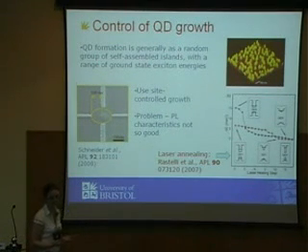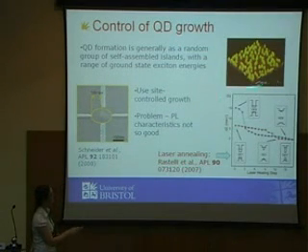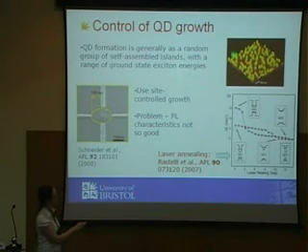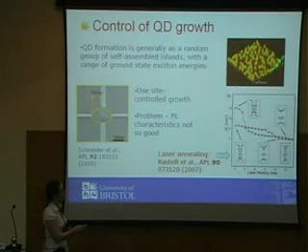So quantum dots then, the ones that we look at, these are self-assembled quantum dots. And self-assembly is a crystal growth technique which produces very high-quality quantum dots. So what you do here, I'm showing you an AFM image of these quantum dots. What we do is deposit indium arsenide slowly onto gallium arsenide. And that allows the formation of these so-called nano-islands here. Now these islands form spontaneously, and they're in a random placing on the crystal structure, and they also have a random size. And that size determines the emission energy of the quantum dot. So even though these have very good optical emission properties, this is not what we want. We want to be able to control exactly where our quantum dots are and what wavelength they have.